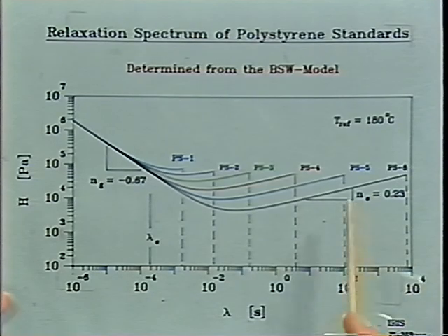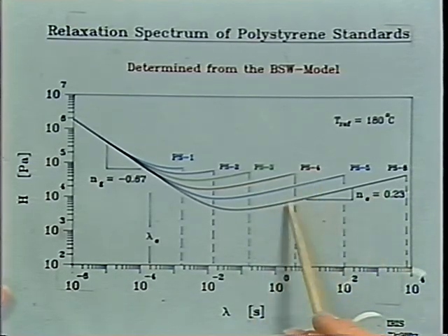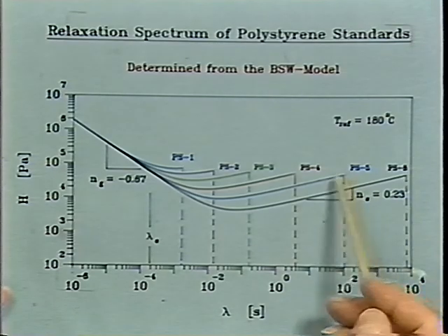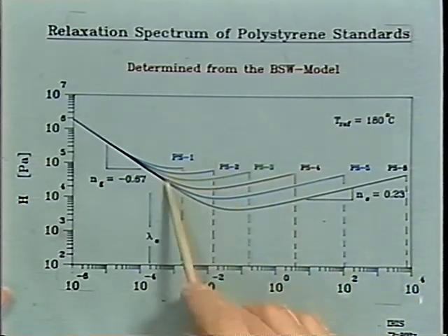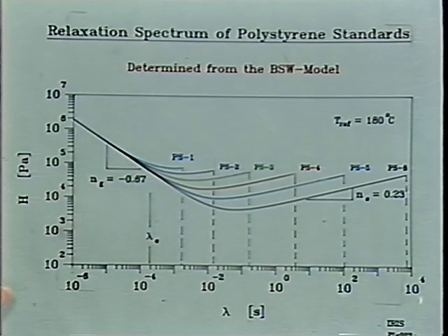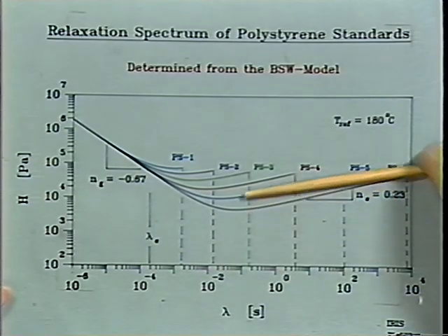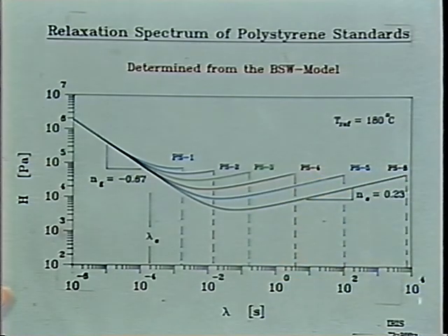So you see all curves have the same shape, the same slope here, and the top point has about the same height, and then in this region there's already interference with the glassy region. The slope of those lines is about a quarter. It's about 0.2, 0.25 in that order. We don't know whether it's a material parameter or whether it's a universal constant. It would be nice to have universal constants, of course, but we have to do more experiments to find out about this. But this is the spectrum, and it has a very nice pattern.